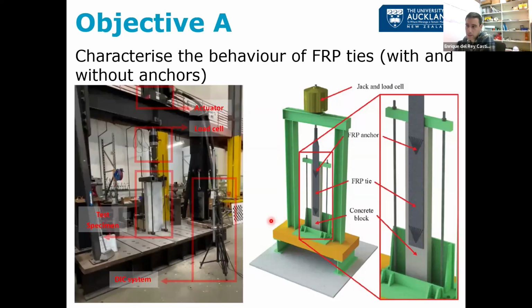It's a very basic test setup. It's just a concrete block that we prevent from moving up with those steel plates or steel square sections, and we prevent them from moving out of plane with a roll in the back. And then we have the FRP here, and we pull from the FRP up. This is a schematic of the same thing. And then we have anchors in different configurations. You cannot see the FRP in there because we painted it.